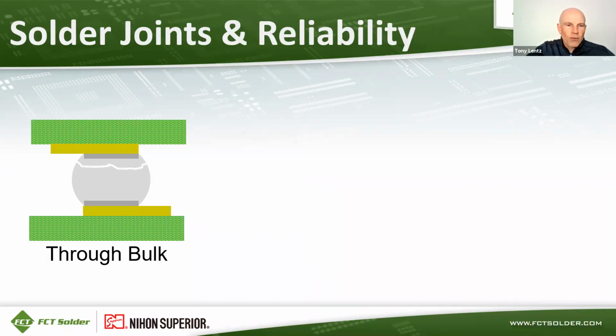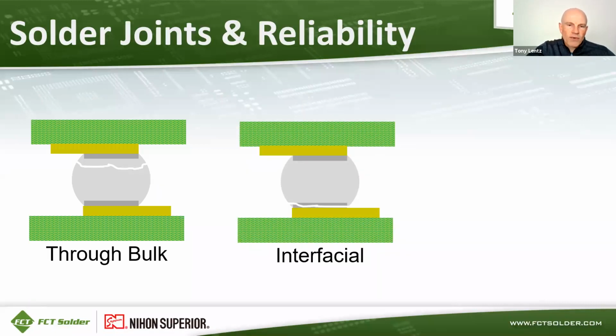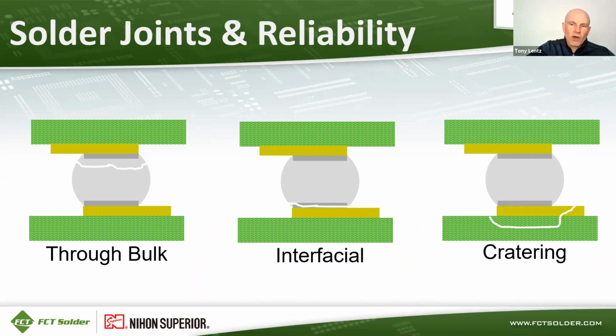Solder joint failures can occur through three major mechanisms. The first one is through the bulk of the solder joint, which is pictured here on the left. The second major failure would be an interfacial failure, or solder joint failure through the intermetallic layer between the solder bulk and the board pad, or the solder bulk and the component interface. Or third, you can get what's called pad cratering, where the pad actually rips off of the circuit board during thermal cycle or mechanical shock and vibration testing. And that indicates that the solder joint was quite strong, but the circuit board material was the weak spot in that particular assembly.